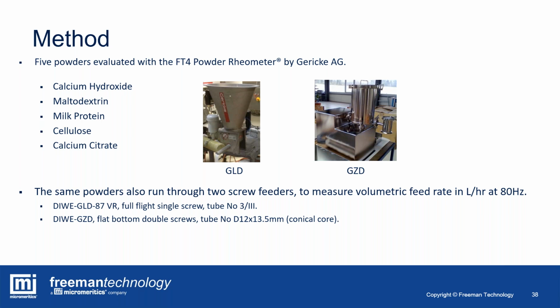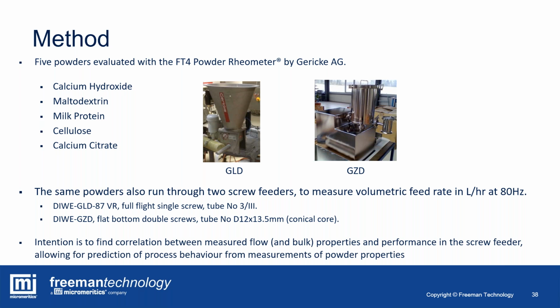And again, these are sophisticated operations or units. However, we can configure them to operate in just a volumetric feed mode. So we just set effectively the screw speed to rotate at a fixed rate for a given duration. And in that way, it can operate in a volumetric mode of operation. And the intention was to try and find a correlation between the measured material flow and bulk properties and the performance in the screw feeder, allowing them to predict the process behavior from measurements of the powder properties.